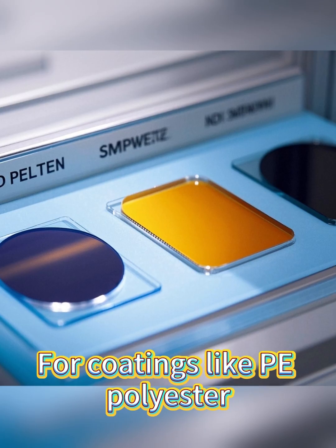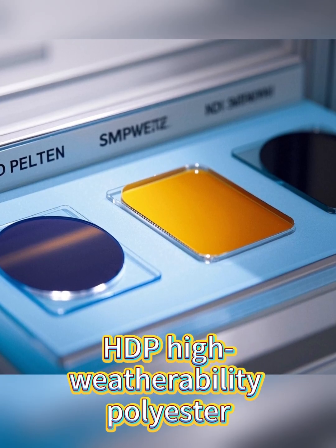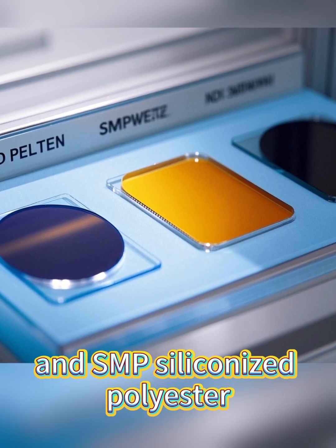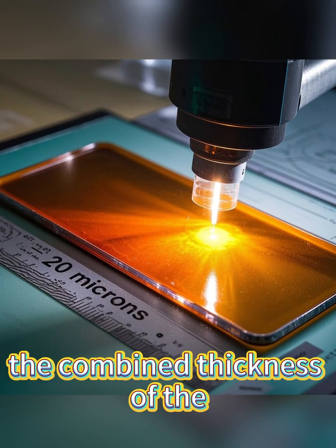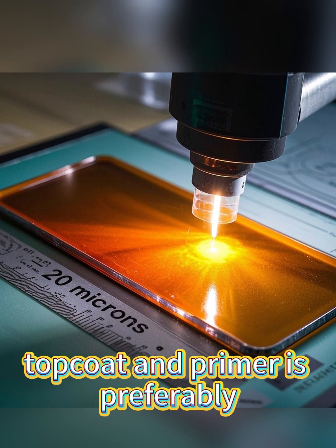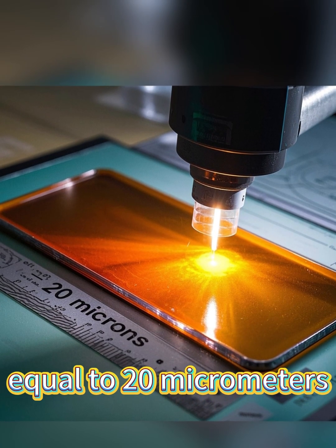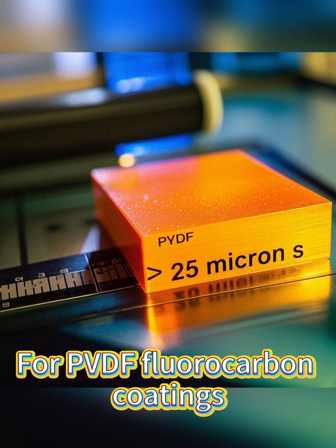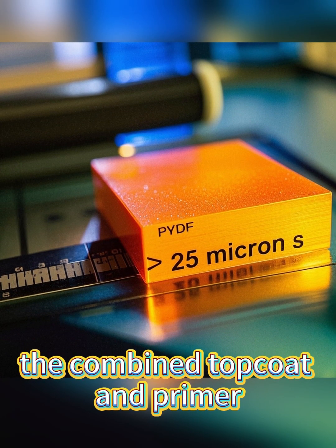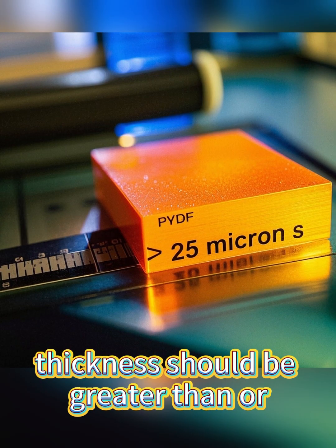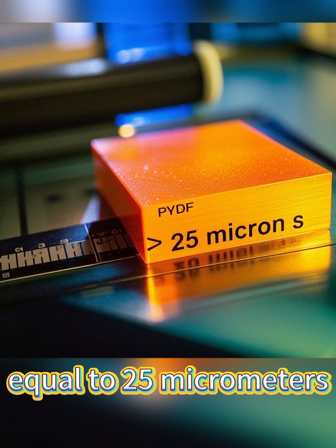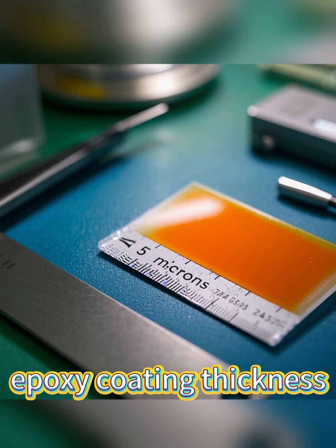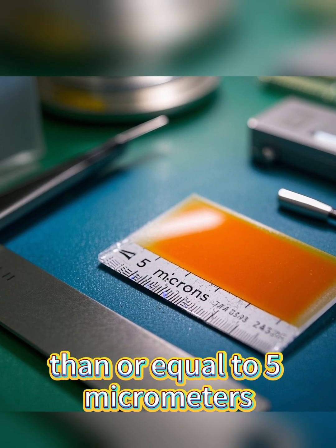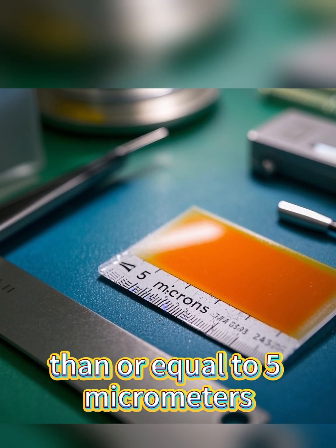For coatings like PE polyester, HDP high weatherability polyester, and SMP siliconized polyester, the combined thickness of the top coat and primer is preferably greater than or equal to 20 micrometers. For PVDF fluorocarbon coatings, the combined top coat and primer thickness should be greater than or equal to 25 micrometers. The backside epoxy coating thickness should be greater than or equal to 5 micrometers.